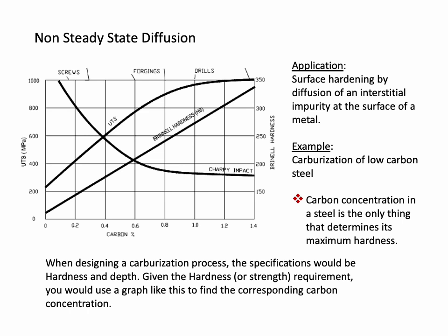You can see hardness and tensile strength are somewhat parallel in the lower concentrations of carbon. In real life applications, it would be rare that you would diffuse or create a concentration of carbon more than 0.8. And so the really practical part of this graph would go from here to here.